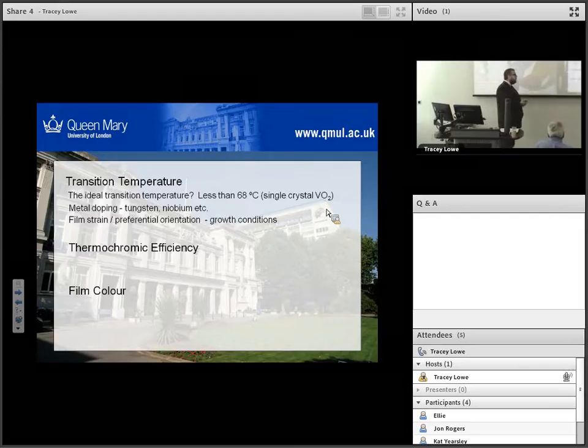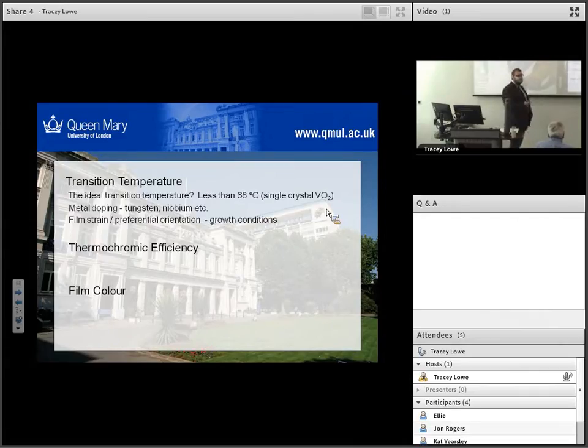Also, we can grow films with some strain, some preferential orientation, and we can lead to a change in our transition temperature as well. We can actually do some of that by controlling our crystallite size.